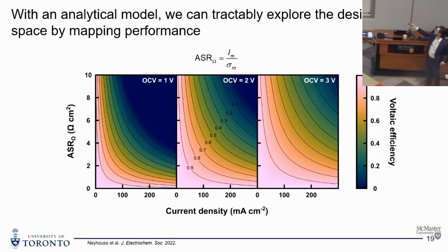This is pretty typical of what you might see in an aqueous flow battery. But if you transition to non-aqueous electrolytes, which have a larger voltage window, like a lithium-ion battery, this expands our window, but also materials tend to be more constrained in this region. And here we're just looking at 3 variables, but you can imagine the extent we can do with a much larger set of parameters and a much larger design space. And this allows us to really easily map these performance characteristics in what is ultimately maybe a couple minutes to get to something like 8,000 data points in each one of these plots. So it allows us a lot more flexibility in making performance predictions.